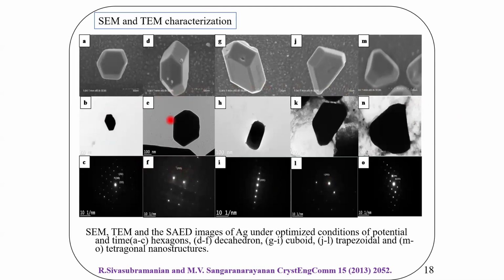Sir, why are you showing this? It is to show that simply by applying a potential with silver nitrate solution on a working electrode, you get all the geometry. There is no other technique better than this to get nanostructures, because there is no high temperature and no exotic solution. Simply apply a potential, take a silver nitrate solution and one electrode, that's all. Nothing else. That is the power of electrochemistry, where you can synthesize exotic materials by simple techniques.